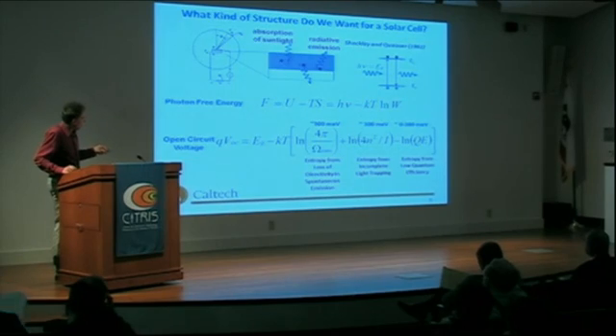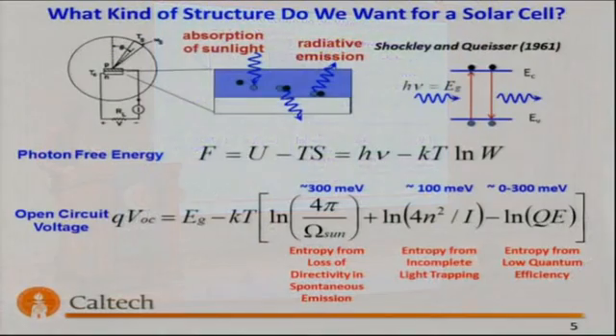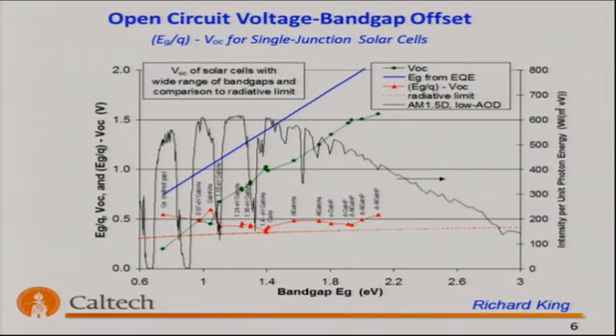These entropic terms here are due to loss of information due to loss of directivity, incomplete light trapping, and also quantum efficiency. If you go through and look at the logarithm of each of these factors and multiply by 25 millivolts, you can convince yourself that there's a loss here, an energy difference between the band gap energy in a semiconductor and the open circuit voltage, that now could be anywhere between 400 millivolts and maybe even a volt in a very low quantum efficiency material. So that's a huge penalty to pay in a solar cell, particularly if you have some prospect for improving and mitigating these loss factors. And this is not just theory.